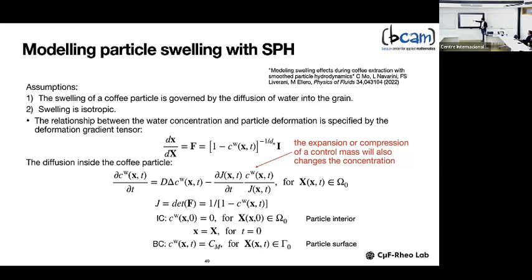We propose a simple model of the deformation gradient tensor, which characterizes the swelling. These are the initial positions, and this is the position after the displacement, after the deformation. We assume that it is proportional to the identity matrix, so the swelling is isotropic. And it depends on 1 over 1 minus C, which means that the larger the water concentration, the larger the swelling. If C equals 0, there will be no swelling. If C approaches 1, there will be infinite swelling.